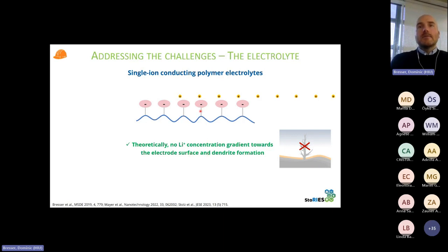This we can avoid, right? Because the anion is fixed, and due to charge balance reasons, basically, the cation cannot just move away from the anion and leave it behind. So this absence of concentration gradients towards the electrode surfaces results, theoretically at least, in the absence of dendrite formation. So that's a great promise. And in fact, what we frequently see is indeed a more homogeneous lithium deposition.